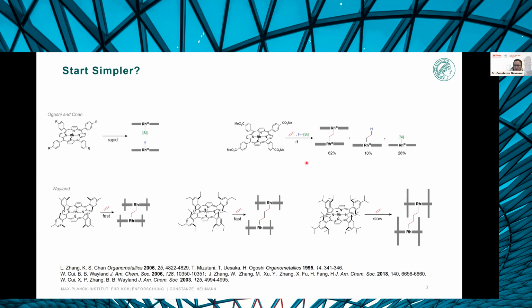And one approach that often is very beneficial in homogeneous catalysis is that you simply increase the steric bulk around the reaction site in order to shut down some processes that would be destructive. For example, dimerization of the complexes via rhodium-rhodium bond formation. That's something that you can readily inhibit by just having bulkier substituents. So while this complex dimerizes in solution, once you have steric bulk on the ligand set, you get this complex monomeric in solution. But once you add ethylene to it, it very quickly reacts with 2 rhodium molecules reacting across the ethylene to make rhodium-3 intermediates. And even if you increase the steric bulk further and even further, you still cannot shut down this dimeric reactivity.